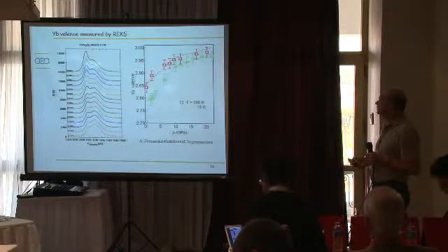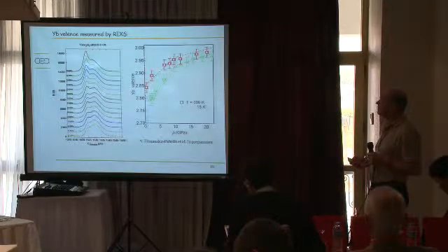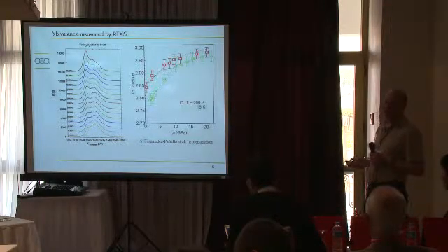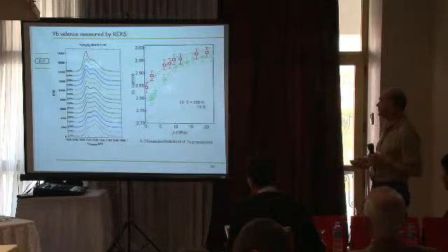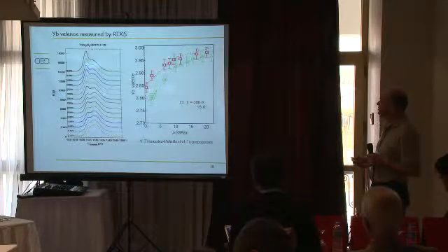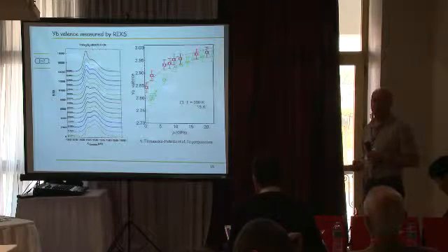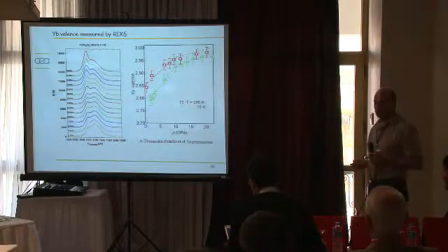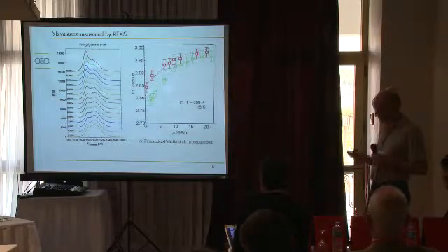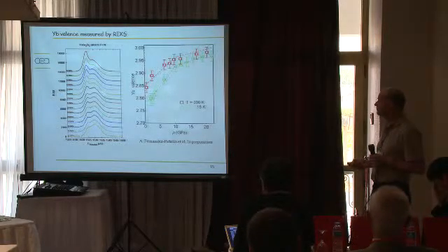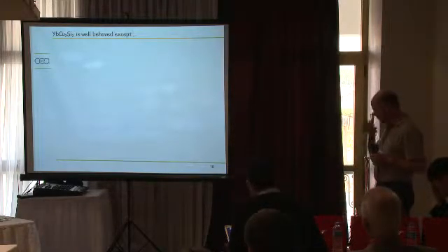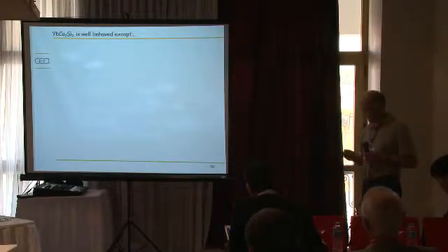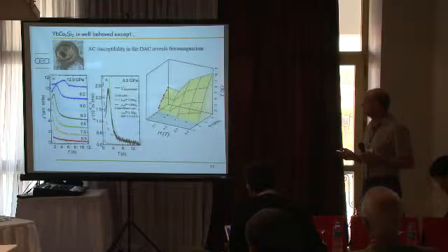But the valence continues to increase, so magnetic order actually sets in before we reach the Yb 3+ state, and the valence is increasing basically across the whole phase diagram we measured, which justifies, if you like, that YbCu2Si2 seems to be following the Doniach picture. So YbCu2Si2 appears to be a well-behaved system, except for a few points.